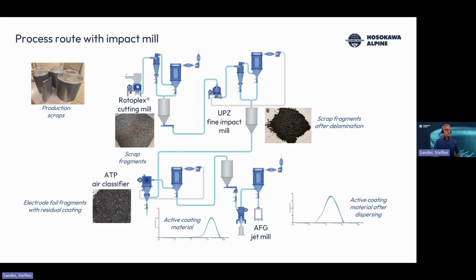One process route I would like to show you is this one using the fine impact mill. So the material that comes here is first of all, as I said, transferred into a bulk material using the cutting mill. You see the material down here that's coming out of such a mill. It's fragments below 1 centimeter, and these fragments are then fed to the fine impact mill. These impact mills are used also in end-of-life recycling. We've delivered real big mills for these end-of-life recycling processes. But in this process, the process conditions are much gentler compared to the end-of-life recycling.